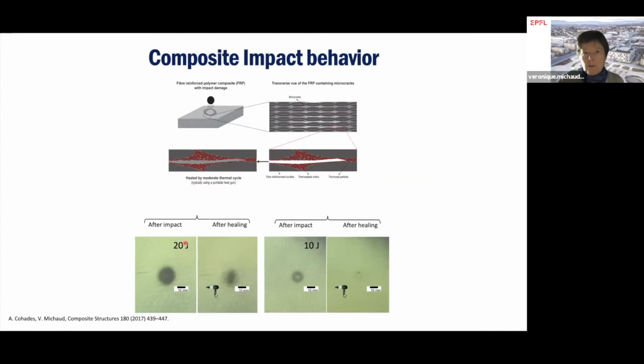So we did this experiment of an impact where we expected the healing to take place, and we checked already visually with glass epoxy PCL composites that after healing, the damage impact started to disappear, and if the energy of impact was not too high, after moderate healing, we could see already that it disappears completely.